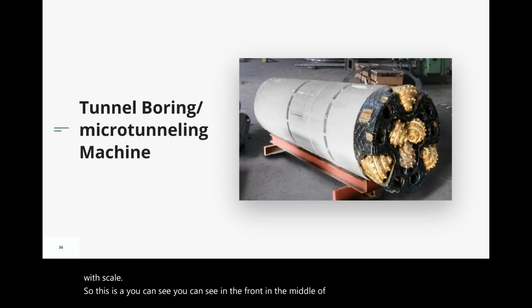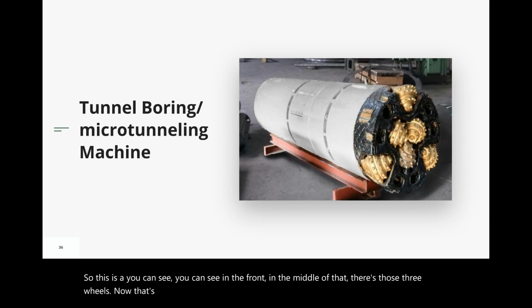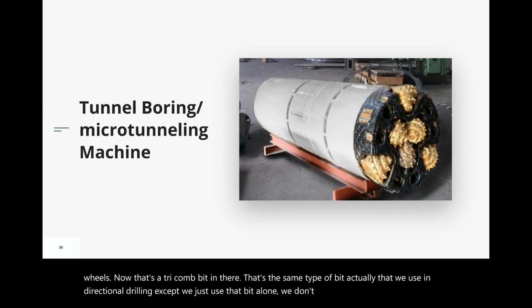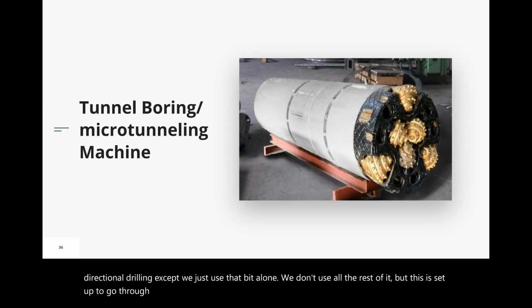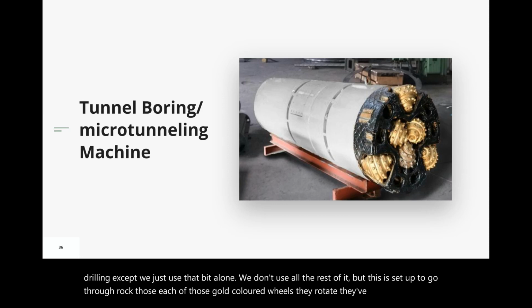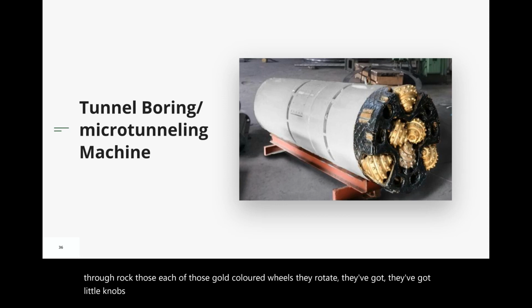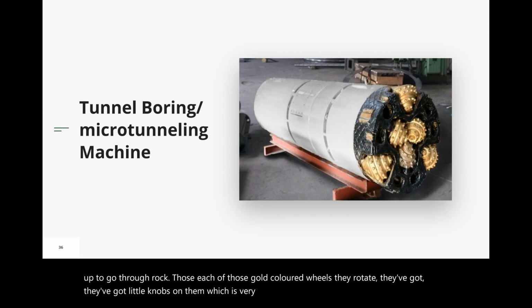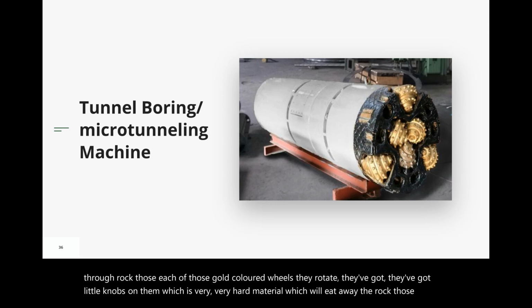Those wheels turn, and they chew away at the rock, and that rock cuttings then, again we use bentonite in this, so that area in front is all bathed in bentonite, shall we say, and the bentonite keeps those cutting edges cool. It also mixes with the cuttings, and it gets pulled back in and dragged back to the surface and separated out. We use the bentonite again, so very similar to the directional drilling system. We use the same in micro tunneling.